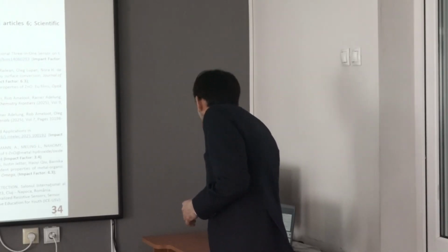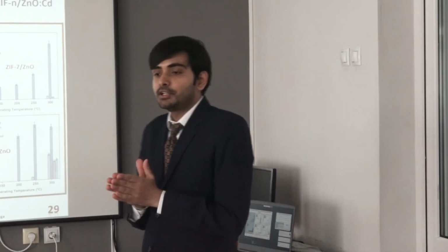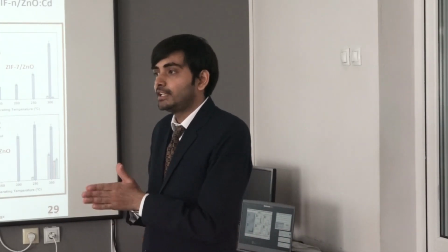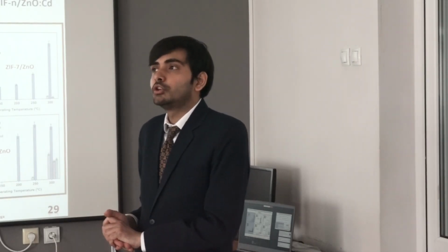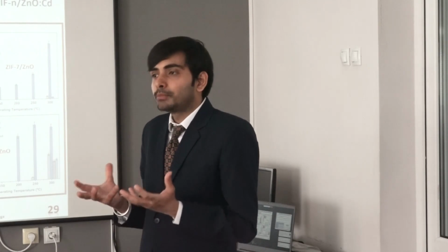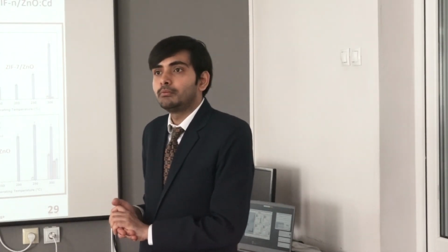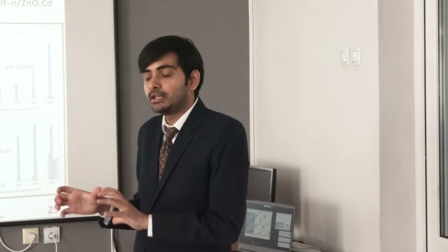And about your third question, if I'm not wrong, it was related to using the Scherrer equation in different chapters, going from chapter 3 to chapter 5. Yes. For example, in chapter 3, ZIF-8 particle size was 70 nanometer, which was less than 100 nanometer. So definitely, as per the literature, there is very less possibility of high errors. Up to around 100 nanometer, it can give appreciable results. So the Scherrer equation can hold good, at least for chapter 3 ZIF-8 particles with the current particle size.